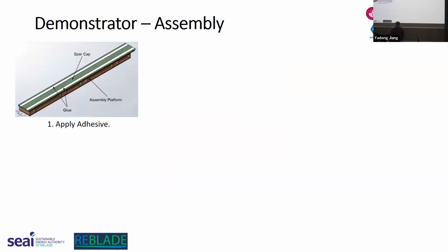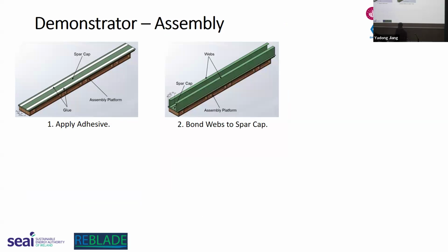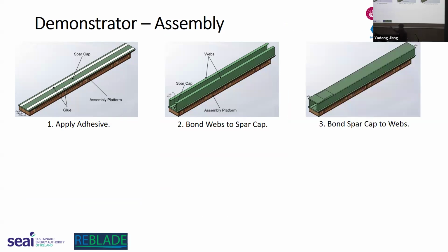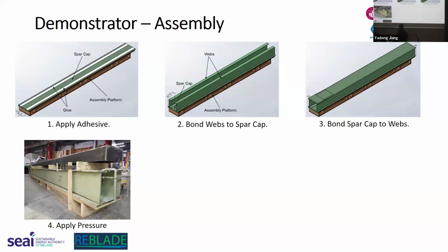Demonstrator assembly. First we apply the adhesive to the bond lines, and then we place the two C-profile webs in position. And then finally we bond the spar cap to the webs. I have some real photos here of applying the pressure. Once we have the webs bonded in place and the spar cap bonded in place, we apply some weight on the top just to consolidate the adhesive.